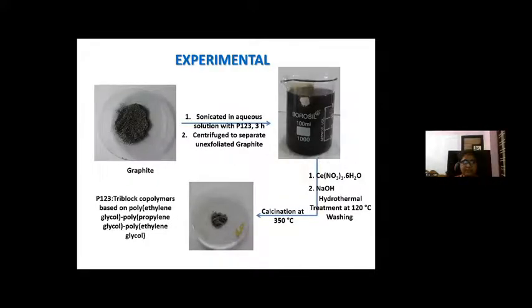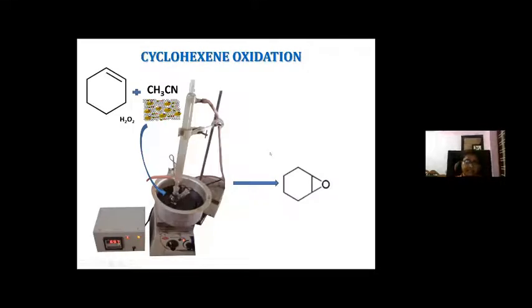About the experimental procedure for the preparation of the nanocomposite, the graphite is sonicated in aqueous medium, and we are using, as already mentioned, P123 as the surfactant for the exfoliation. After 3 hours of sonication, the unexfoliated graphite is separated, and then cerium nitrate is introduced, and for the hydrolysis, sodium hydroxide is also used. Then it is hydrothermally treated for the composite formation, and after calcination, we get CeO2 incorporated graphene. Next is the catalytic reaction. Here, the solvent used is a green solvent, acetonitrile, and the oxidant is hydrogen peroxide, as already mentioned, and we started the synthesis of cyclohexene epoxide.